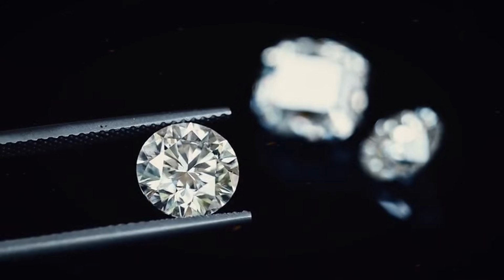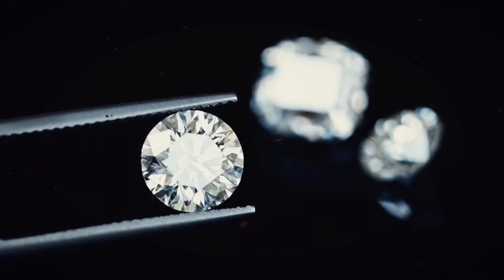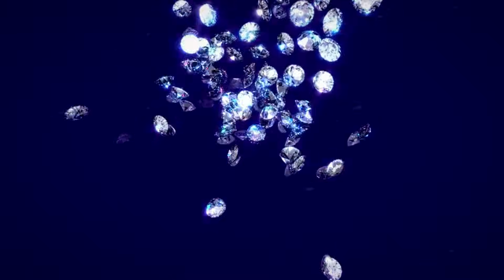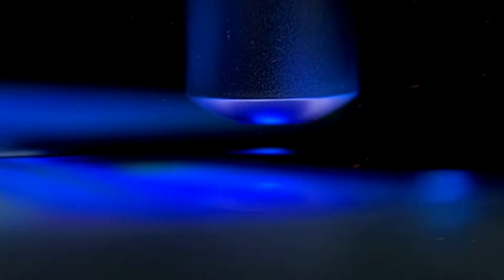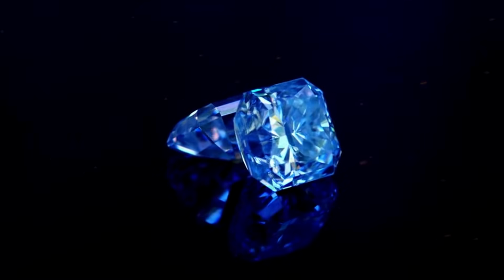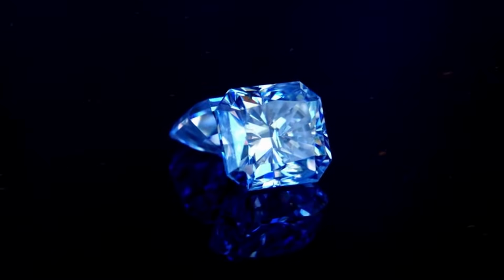Roughly 25 to 30% of natural diamonds exhibit some level of fluorescence under UV. That means the majority, perhaps surprisingly, do not. So while a blue glow under long-wave UV might align with a natural diamond's profile, its absence doesn't disprove authenticity. And the presence of fluorescence alone isn't proof either. Several simulants, including synthetic spinel and moissanite, can also fluoresce, sometimes even more brightly.